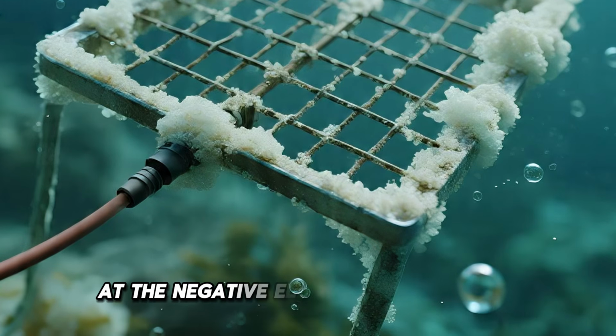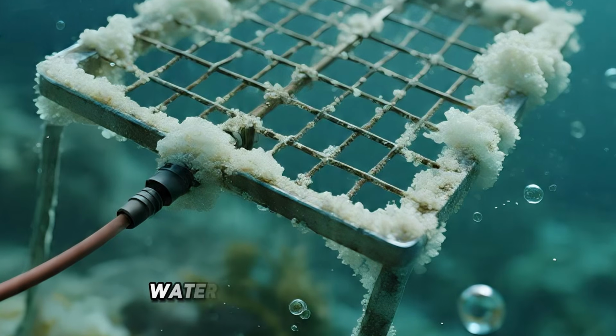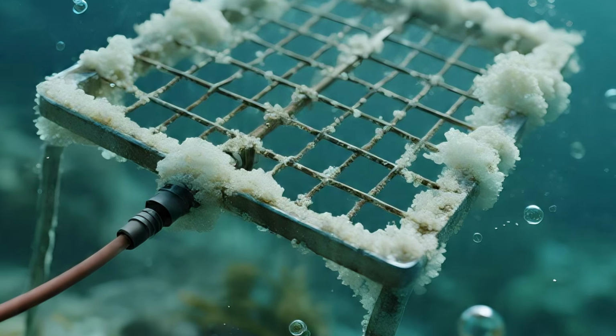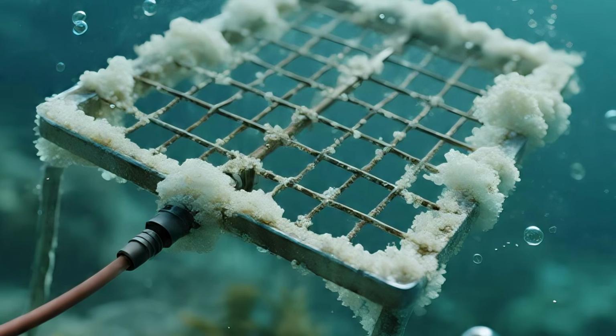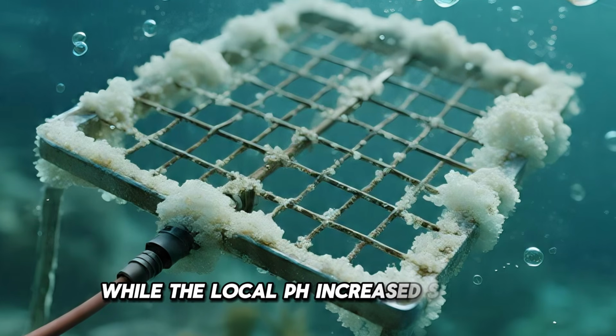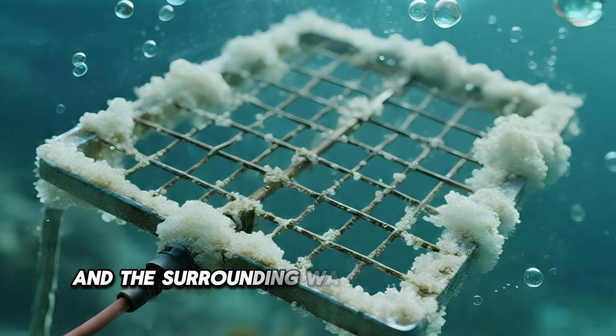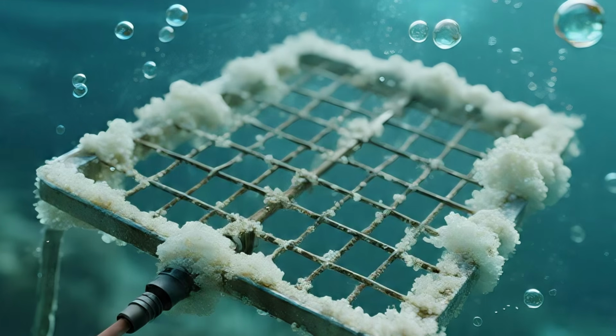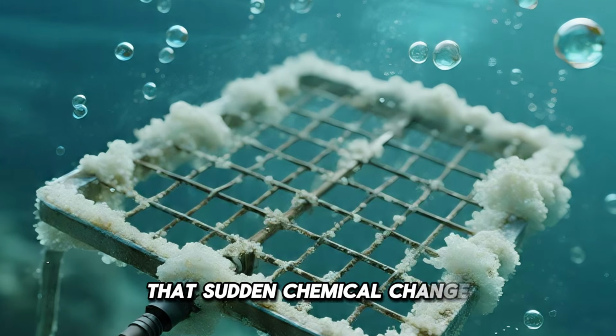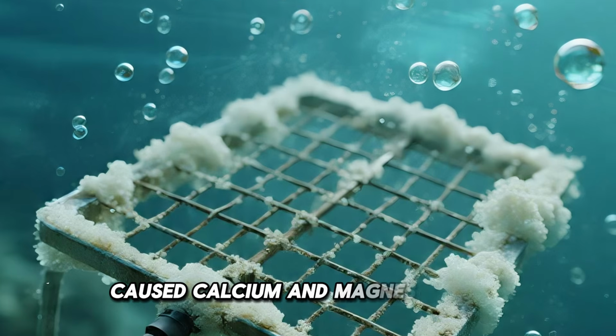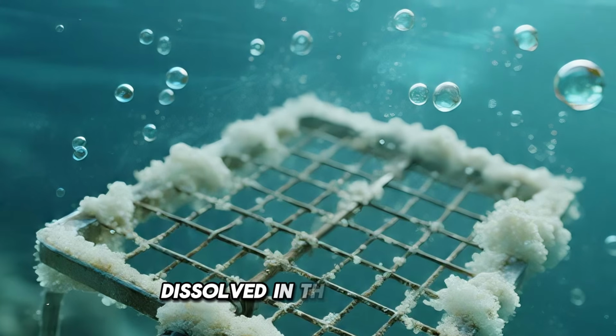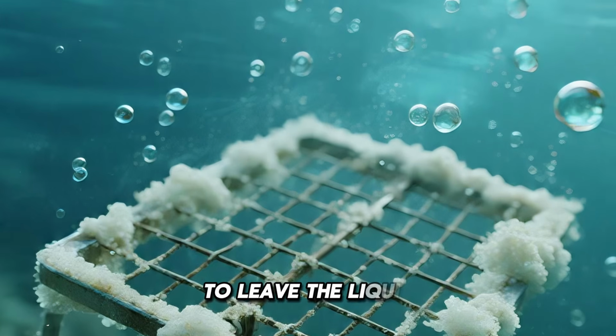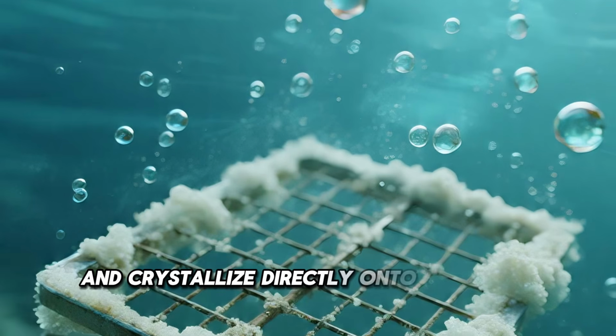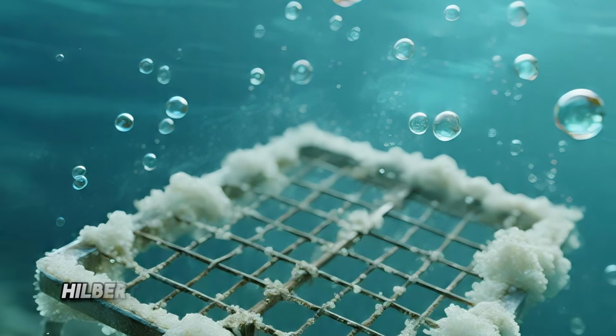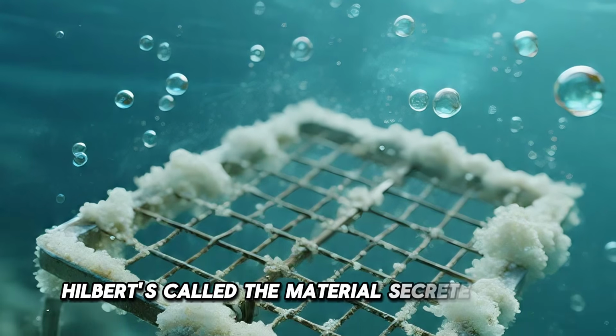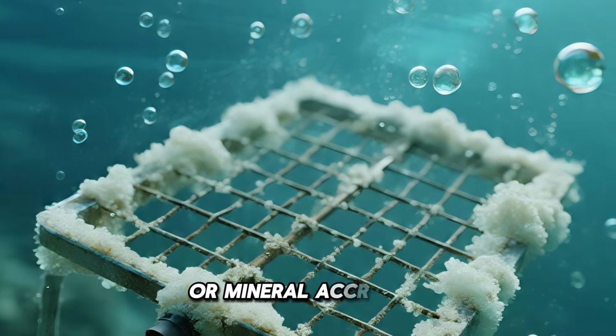At the negative electrode, or cathode, water molecules split apart. Hydrogen gas was released, while the local pH increased sharply and the surrounding water became highly alkaline. That sudden chemical change caused calcium and magnesium ions dissolved in the seawater to leave the liquid and crystallize directly onto the metal framework. Hilbertz called the material seacrete, seament, or mineral accretion.